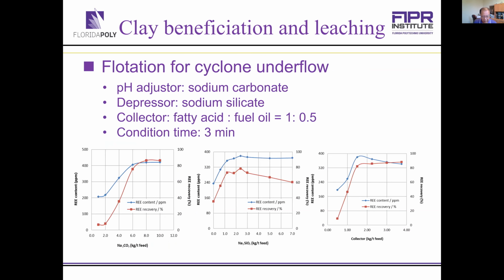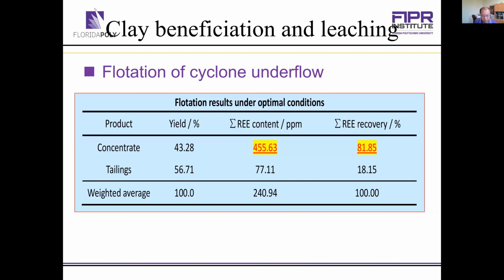For the cyclone underflow product, because we removed much of the clay particles, we can use a flotation process to further concentrate phosphorus and rare earth containing materials. This shows the effect of acid collector dosage and also depressant dosage. As you can see, in most cases, we got good recovery. The red line represents recovery of rare earth. It's over 80% by this flotation process. So by this flotation, we concentrate the rare earth concentration up to 455 ppm. The total recovery in the concentrate is almost 82%.